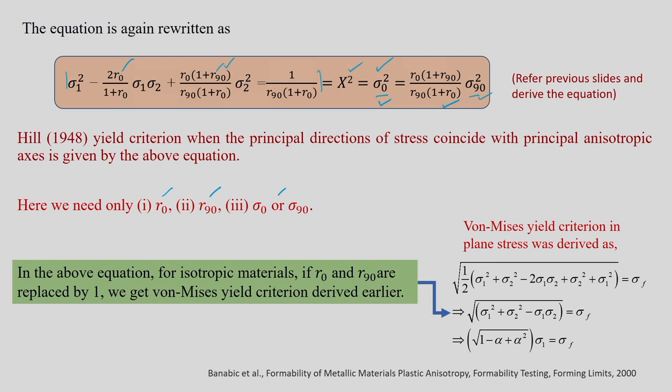Okay, it is very simple to use. This particular criterion is very simple to use. R0 you know how to find, R90 also you can find, sigma 0 also you can find. Take a tensile test, do a tensile test along the 0 degree loading direction and find out all the values, right? So, now in the above